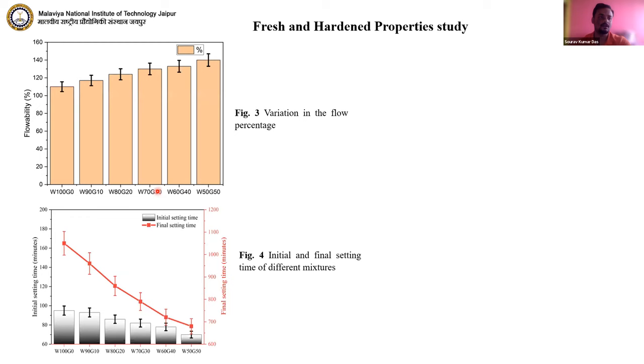And coming to the fresh and hardened property study, this is the flowability study where you can see that all the samples where the glass powder is being used as 10, 20, 30, up to 50%. W100 is 100% waste cement concrete and G0 means glass waste is 0%. We have taken it up to 50% replacement, and with the increment of the replacement, there is an increment in the flowability, which is mainly due to the lower amount of water absorption and the glassy surface of glass wastes.